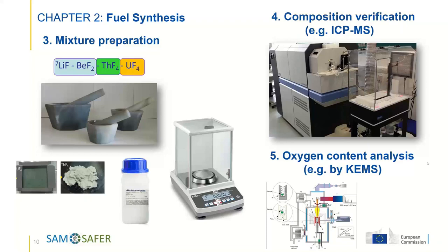We evaporate the fuel completely, and we first see the evaporation of the main fluoride components. And if there is still some residual oxygen, we will see it afterwards, because this technique goes almost up to 3000 Kelvin. It's in an ultra high vacuum, so we can in principle also evaporate oxide fuel samples completely.